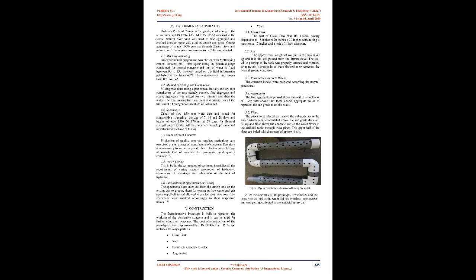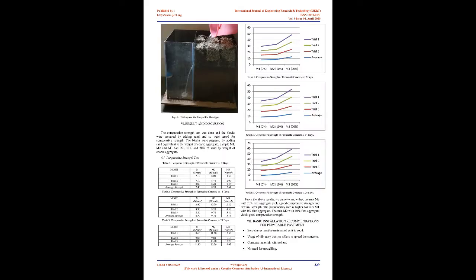4.2 Method of mixing and compaction. Mixing was done using a pan mixer. Initially the dry mix constituents, namely cement, fine aggregate and coarse aggregate, were mixed for 2 minutes and then the water was added. The total mixing time was kept at 4 minutes for all the trials until a homogeneous mixture was obtained.